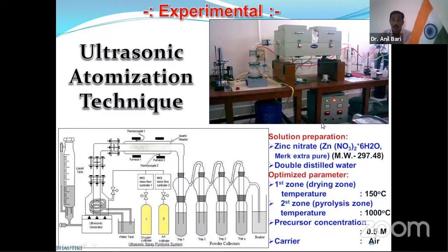This is the actual photograph of the ultrasonic atomization technique, and this is a schematic diagram of the ultrasonic atomization technique. This technique includes the ultrasonic generator. This is an ultrasonic generator which includes the piezoelectric transducer. There are 3 piezoelectric transducers. This is a liquid tank. This is a 2-zone furnace, first zone and second zone, and this is a trapping system. We can trap the prepared nanostructured powder in this trapping system.